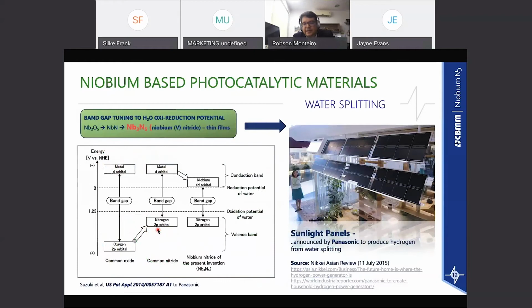It's not surprising that, as I mentioned, Asia is far advanced in photocatalysis. This is an attempt by one of the Japanese companies called Panasonic, which devised this strategy of band tuning of niobium in order to adjust the oxidation-reduction potential of the water splitting. They started from niobium pentoxide and changed to nitrides, and further, they devised a niobium nitride type photocatalyst that had a band gap that matches very nicely the redox potential of the water splitting.